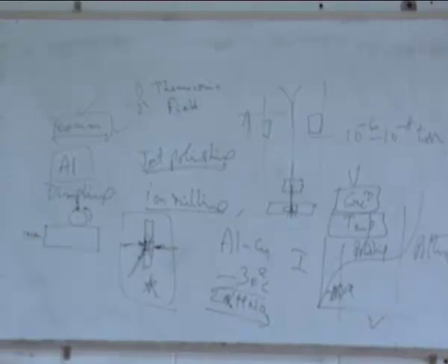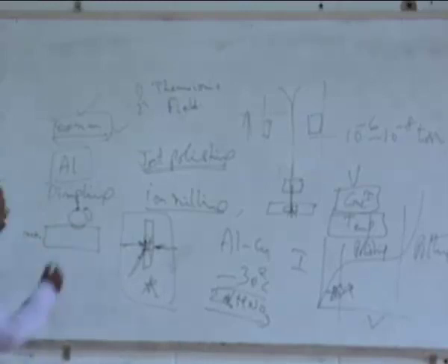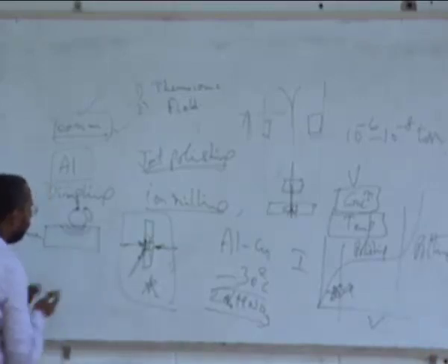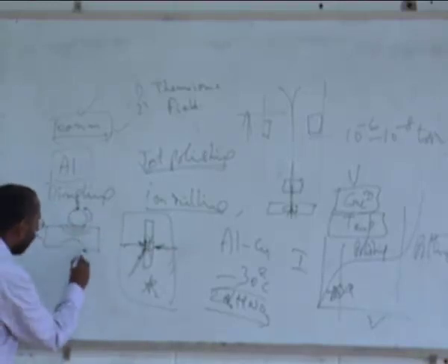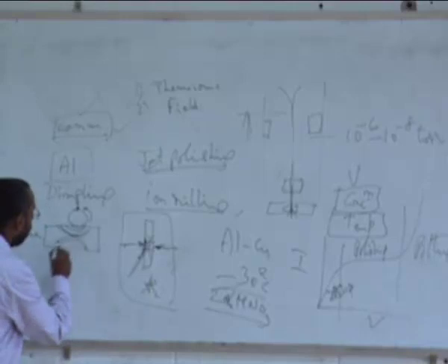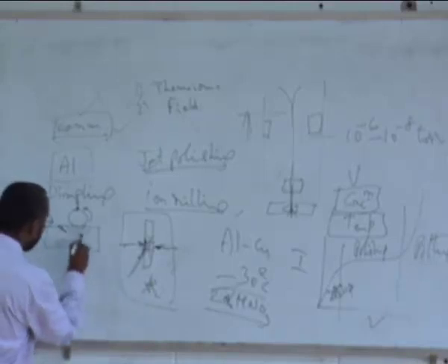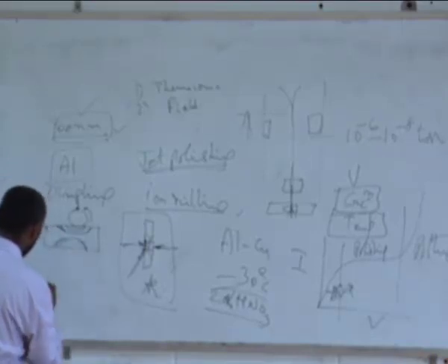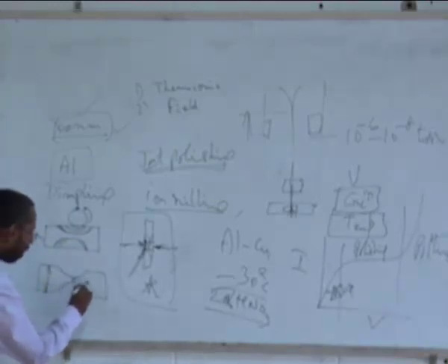And when you do this, what happens? This grinding wheel tries to remove the sample, right? So it forms a kind of dent on the surface. And after it forms a certain dent, if I can invert the sample and do it again on the second side, you will see on the other side also you will form a dent. So you are not interested here in making the hole, but simply interested in reducing the thickness like this, so that now your sample is something like this. So from 100 microns, you have brought it down to around 10 microns.